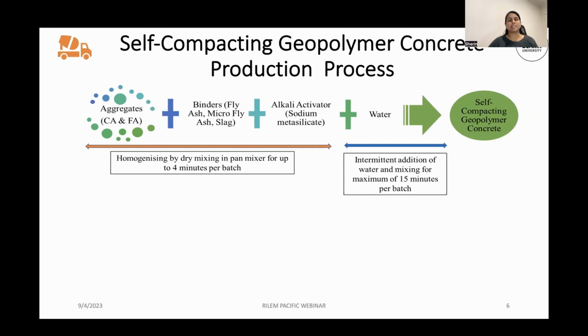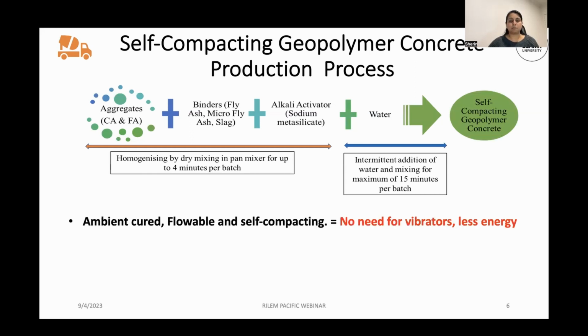When we mix the aggregates and binder materials in the presence of a highly alkaline product, it creates a cementitious activity. And for this process, we make use of sodium metasilicate, which is a highly alkali containing product. By homogenizing these dry ingredients in the pan mixer for up to 4 minutes, we then start to add water. The intermittent addition of water is continued until 15 minutes of mixing of the whole batch. This is found to produce a self-compacting geopolymer concrete, which can be ambient cured and which is flowable and self-compacting.